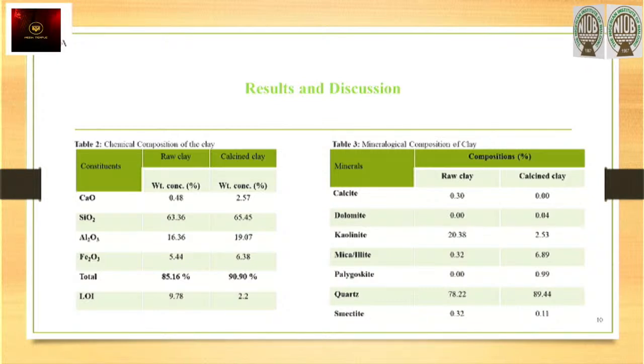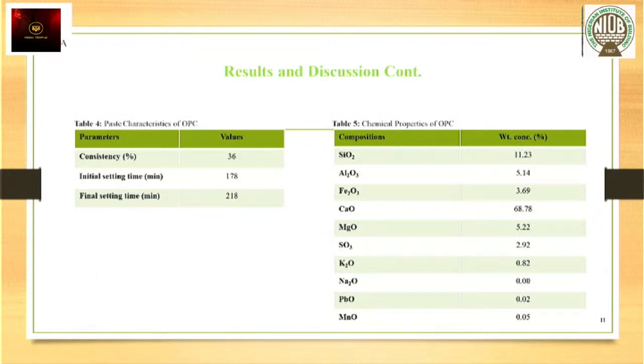The next slide, please. Table 4 shows the paste characteristics of the ordinary Portland cement used. It has a consistency of 36%, initial setting time of 178 minutes, and final setting time of 218. While Table 5 shows the chemical properties of the, sorry, there's a mistake. The chemical properties of the OPC. And from the results, you can see that the calcium oxide, which is a major composition that imparts the cementing property, has the highest, which is 68.78%. Let's go to the next slide, please.